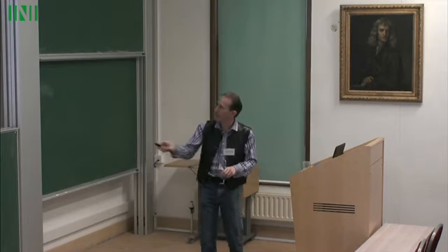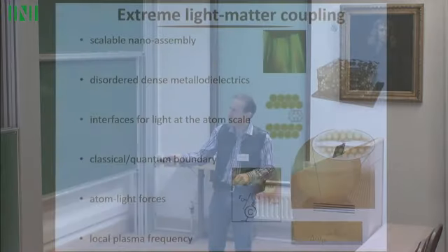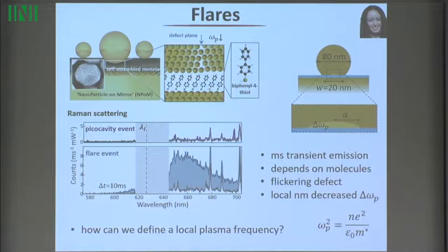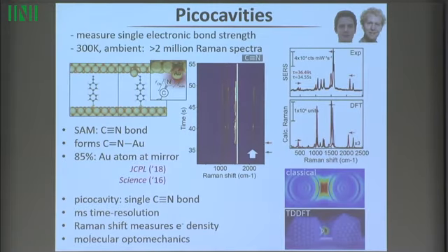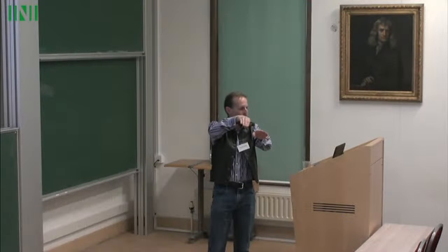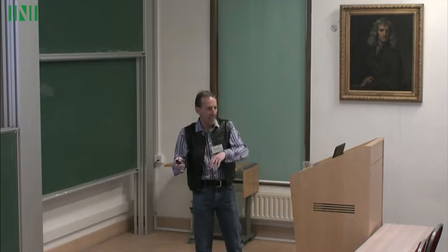When this gold atom moves out here, what you can see are changes throughout the rest of the molecule, and we can track that. You actually sort of see it here directly. These changes are in the rings. There's a whole lot of changes that you can't just see that are in there as well. In fact, what we're doing at the moment is trying to take all this data and reconstruct precisely the position of all the bonds and the gold atom there. We think we can get that gold atom to about a picometer at the moment. For instance, there's a twist around those rings there. They'll twist like that, and we think we get that to about 0.1 degrees. That reconstruction is depending on DFT.